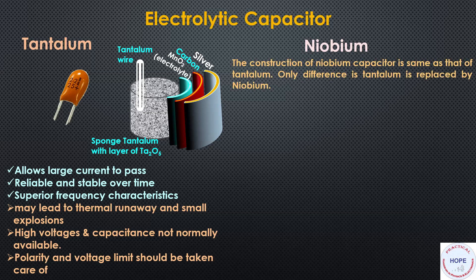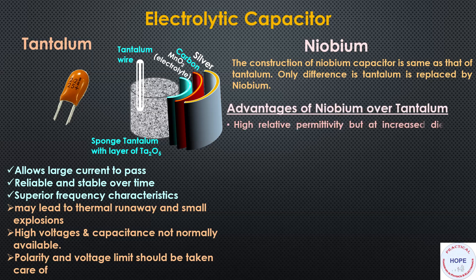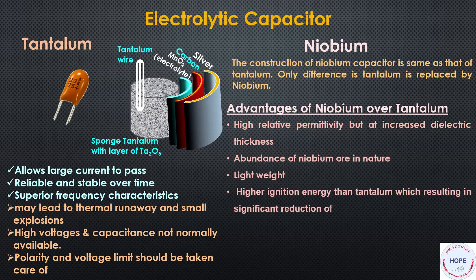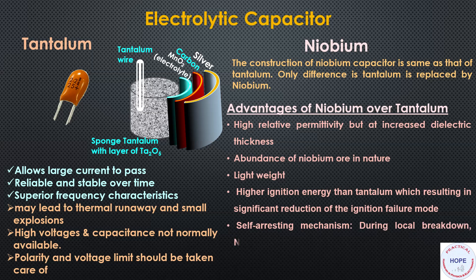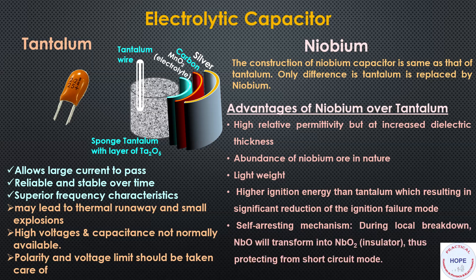The niobium capacitor has the same construction as the tantalum capacitor, with tantalum simply replaced by niobium. Niobium offers certain advantages: higher relative permittivity at increased dielectric thickness, greater abundance in nature compared to tantalum, lighter weight, higher ignition energy reducing ignition failure modes, and a self-arresting mechanism where during local breakdown NbO transforms into NbO₂, thus protecting against short-circuit failure.